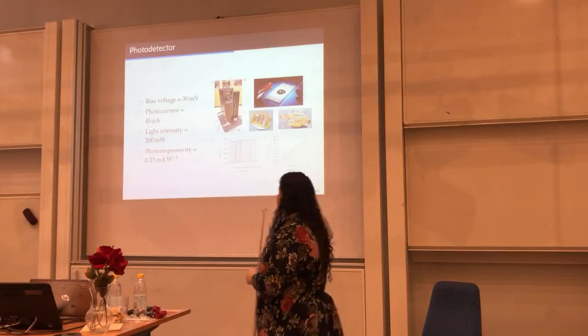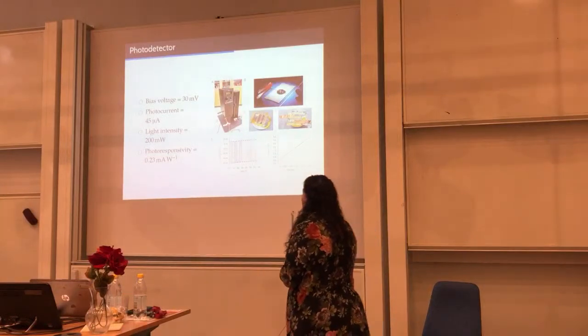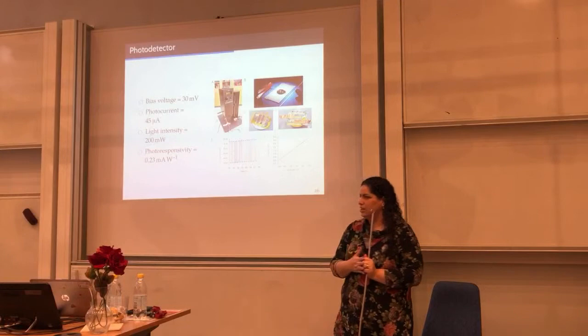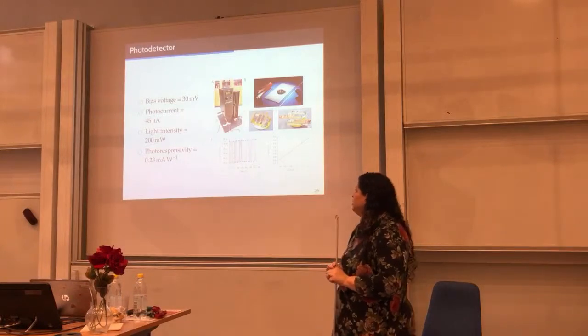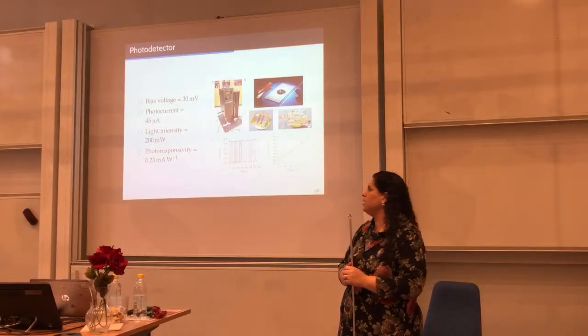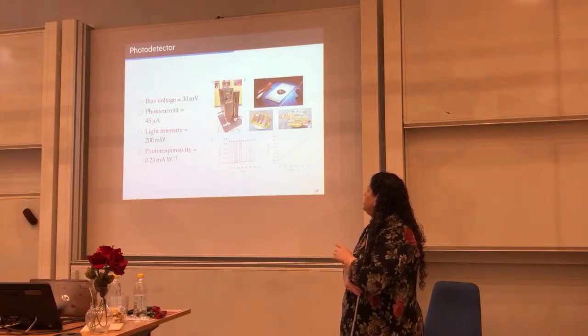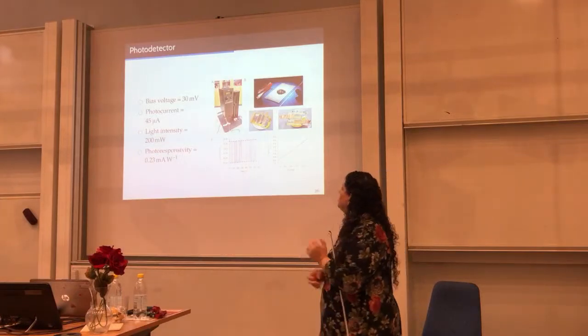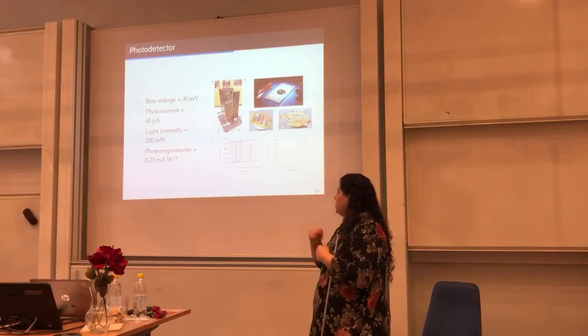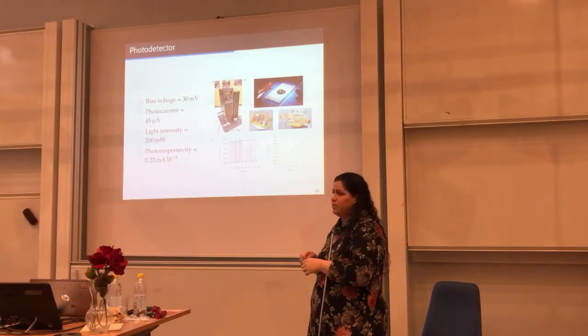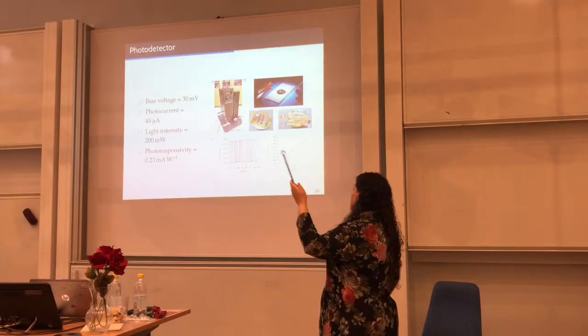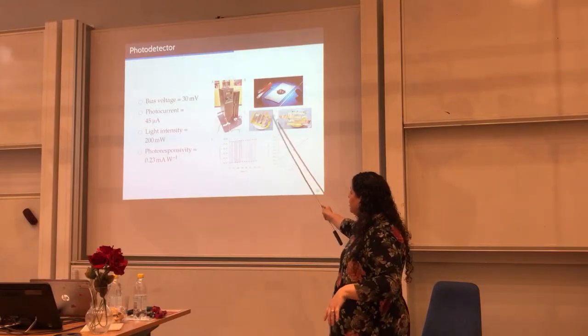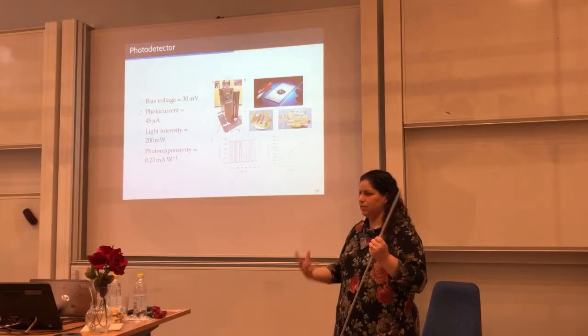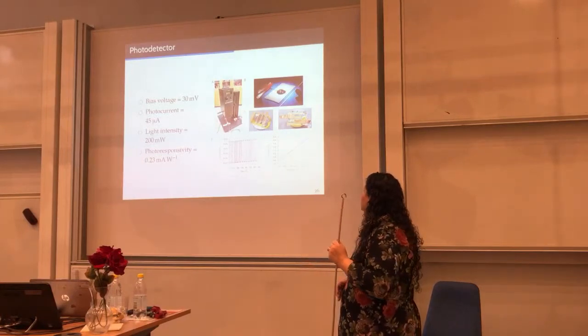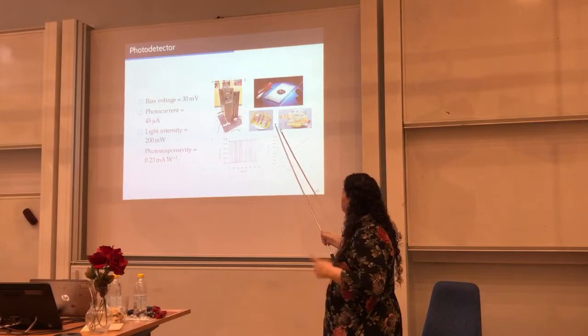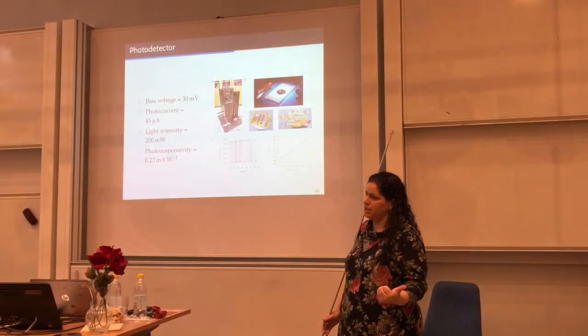All right. The device that I made was not done by inkjet printing, but with a very, very simple method. I got a crystal of more or less this size, and I could just mechanically exfoliate the layers of the molybdenum. And I had a very big flake of molybdenum that I could use to evaluate the optical properties of it. This flake is the same material that I use in my